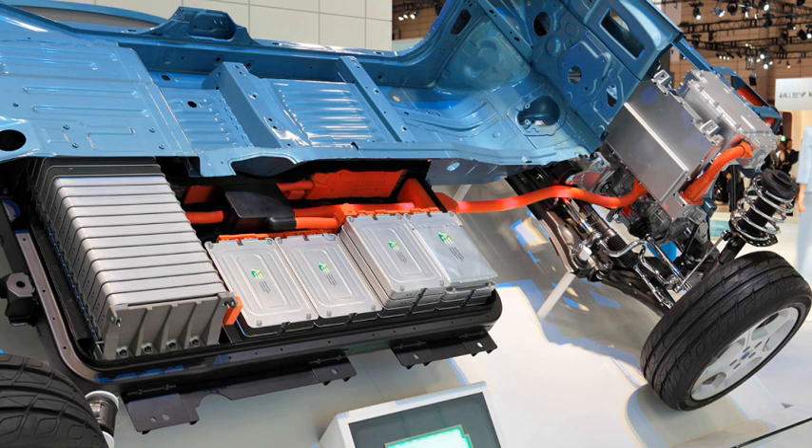The sodium, or "zebra," battery uses molten chloroaluminate sodium as the electrolyte, also occasionally referred to as "hot salt." A relatively mature technology, the zebra battery has a specific energy of 120 watt-hours per kilogram and reasonable series resistance. Since the battery must be heated for use, cold weather doesn't strongly affect its operation except by increasing heating costs. Zebras can last for a few thousand charge cycles and are non-toxic. Zebra batteries have been used in the MoDEC commercial vehicle since it entered production in 2006.